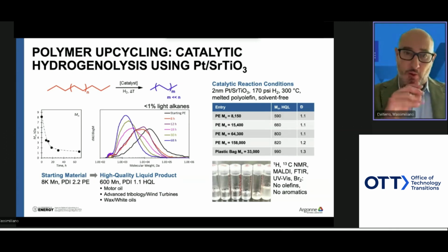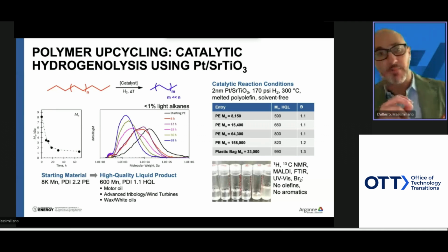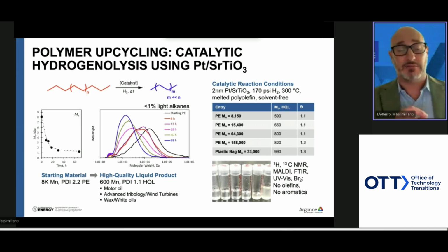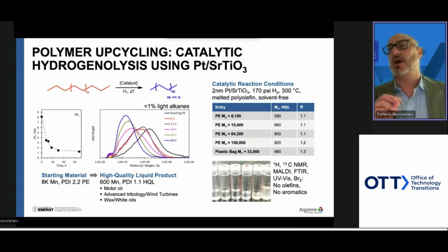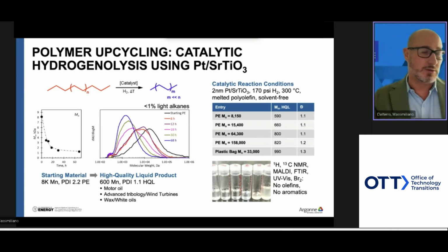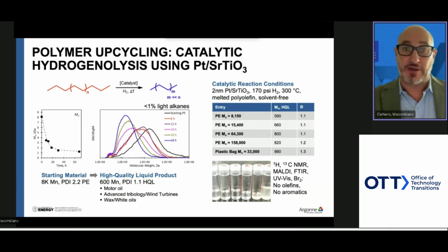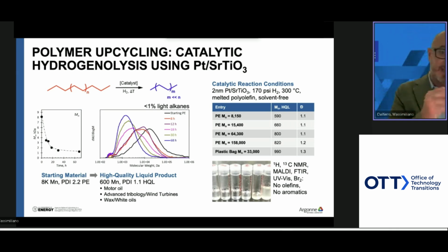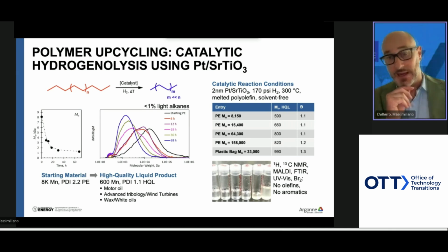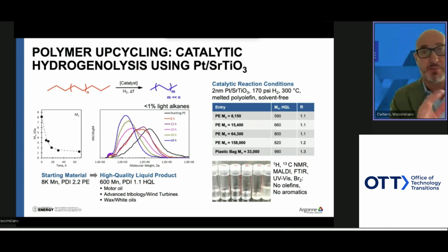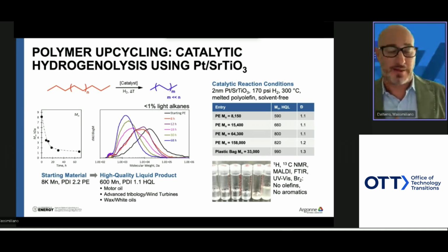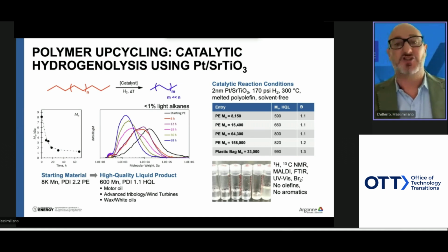The catalysts work with, and this is the first example that we reported, polyethylene, particularly high-density polyethylene as an example without branches, and using a standard product. Lately, we are moving on to real waste, and in fact, I have an example here of a plastic bag. The plastic bag was not clean, and it was used as is, and you can see that the product and the performance of the catalyst are unchanged.